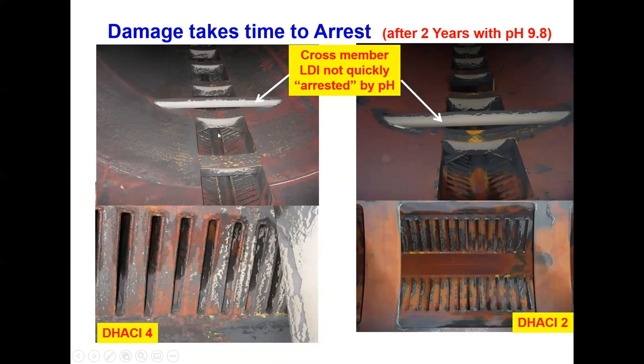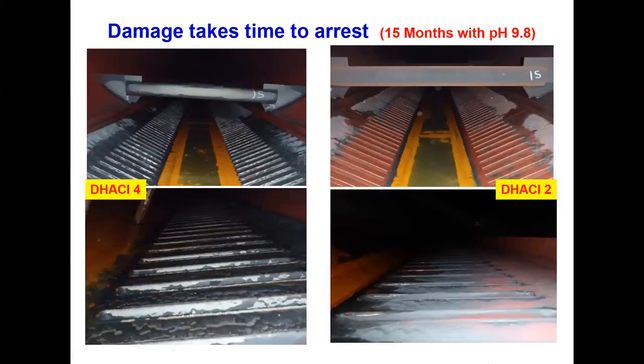Here, the white areas of FAC with a high DHACI. And then after increasing the pH, the FAC improves. We get magnetite formed on these surfaces, a little bit of magnetite on the cross members, and the DHACI, of course, decreases as indicated. So this is one example. Here's another example. Pretty much the same thing.